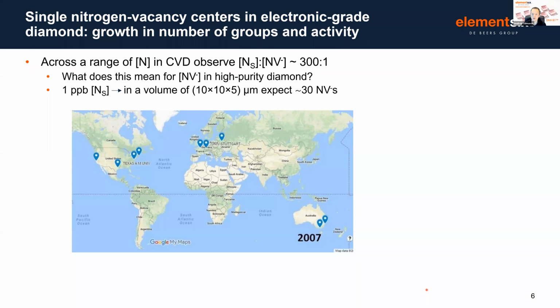So if we backtrack slightly and think about what we've made with electronic grade diamond, we can start thinking about what that means in terms of how many NV centers somebody might find in this material. So as a typical rule of thumb, for a range of nitrogen CVD material, we typically observe a ratio of substitutional nitrogen defects to the negative NV defect, which is the defect and charge state that we're interested in, of around 300 to 1. So if we recall, we said that concentration in electronic grade diamond is typically around 1 part per billion. So what this means is in a volume of 10 by 10 by 5 microns, we would only expect about 30 at most negative NV centers.